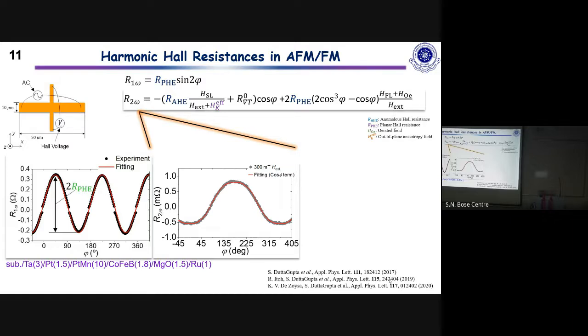The interesting thing about the second harmonic is that it not only gives you the current-induced torques, but looking at the sign of this voltage, you can also get an idea about the sign of the spin Hall angle. So for here it's positive, and if it's the opposite sign, then this will become negative. So it will immediately tell you what kind of spin Hall it is.